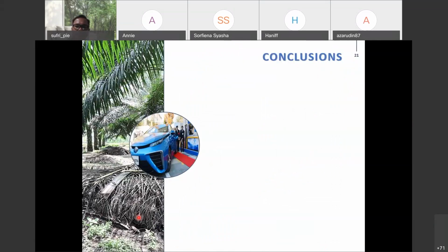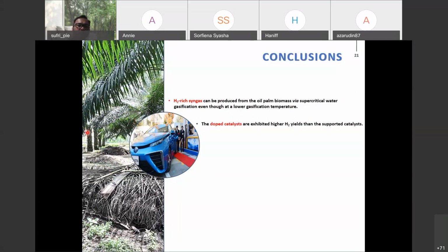I come to the conclusion. We can conclude that syngas rich in hydrogen can be produced from our local biomass, oil palm, by using supercritical water gasification, even at a low gasification temperature of 400 degrees C. The doped catalyst structure exhibited a higher amount of hydrogen yield compared to the supported catalyst. And also, we found the zinc-based catalyst is more active in the reaction for hydrogen production compared to the nickel-based catalyst.